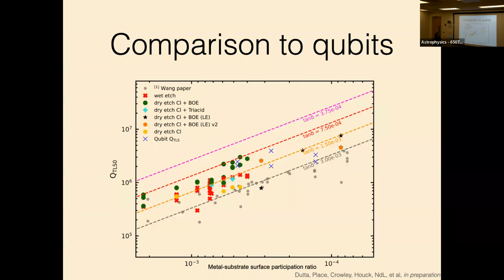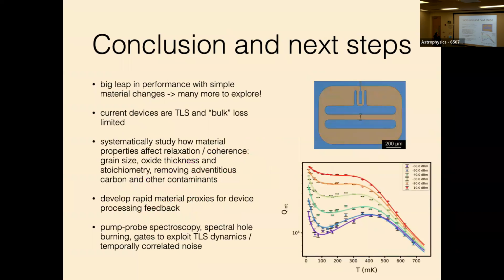And then we can compare to what happens when you make qubits, and we see that we're generally lined up, but then we see this flat participation dependence. So there's something that looks like bulk loss that's creeping in for the largest devices. Okay, let me just skip the next story and say, the conclusion here, I would say, is we saw a really big leap in performance by just trying a new superconductor. I'd say the whole field had done 3, maybe 4 materials, if I'm being generous, for a few decades. And we did a 5th one and managed to beat the record by a factor of 3.